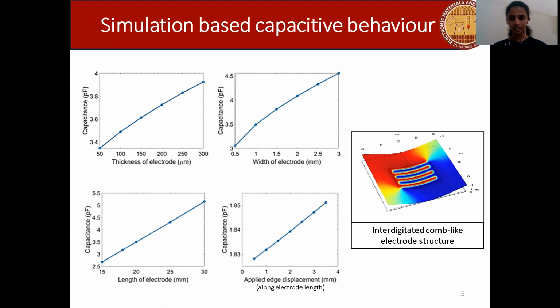Following that, when an edge displacement is applied to the capacitor structure, this device can be bent in two different directions. One about an axis that is perpendicular to the electrodes, and two about an axis that is along the length of electrodes. In the first case, where the axis is perpendicular to the electrodes, when the structure is bent inwards, we can see that there is no significant variation in capacitance, and it almost remained a constant in the range of 1.8 picofarad.